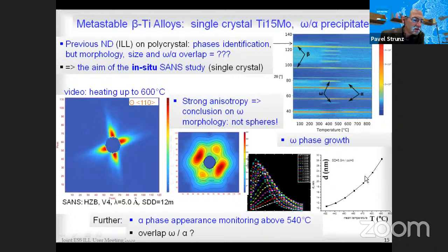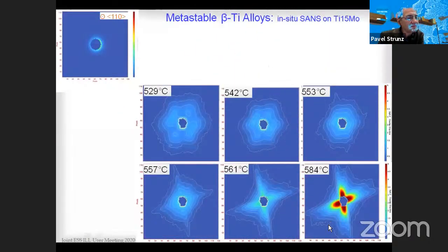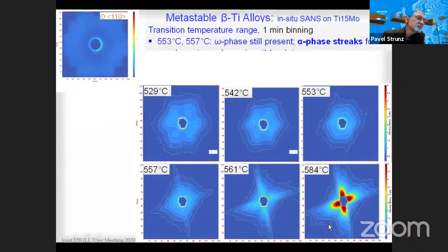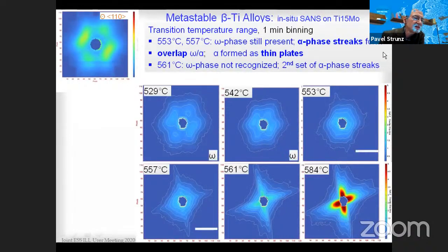depicted here. From my point of view, very interesting is alpha phase monitoring above some temperature level. It is shown in detail in this slide. When we do fine binning of the data, we can see that at 553 degrees centigrade there is omega still present, the same at 557. But already at these temperatures, the streaks from alpha phase appear.